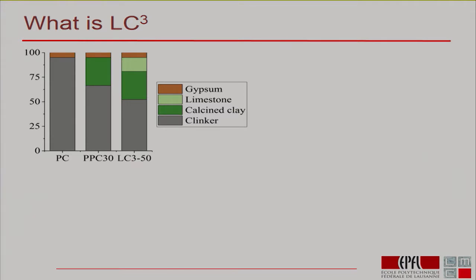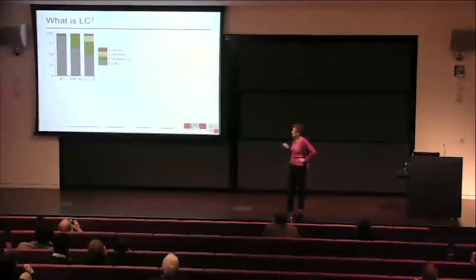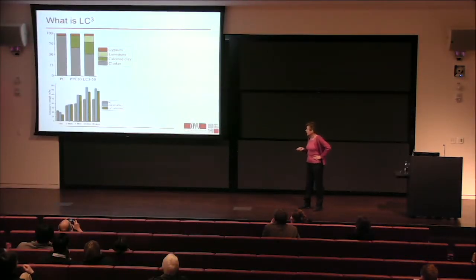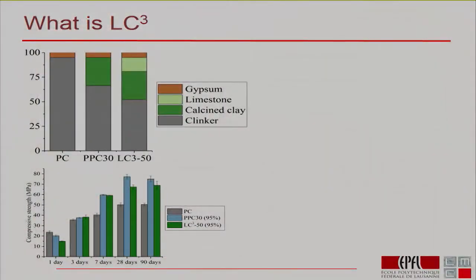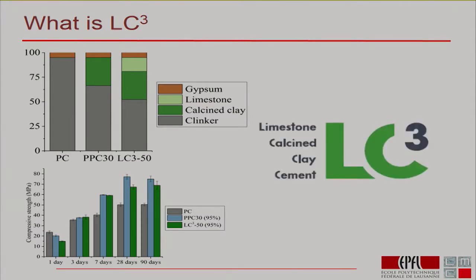And where the breakthrough came was putting this together with the idea of limestone, because it was shown that limestone actually reacts with alumina. So you've got a little bit of alumina in your clinker, but you've got a lot more in your calcined clay. If you put this together, you can go to 50% substitution. And if you look at these typical strength results here, you can see as early as 7 days, these materials, which contain less clinker, less CO2, are giving us higher strengths. So it starts to get really exciting.